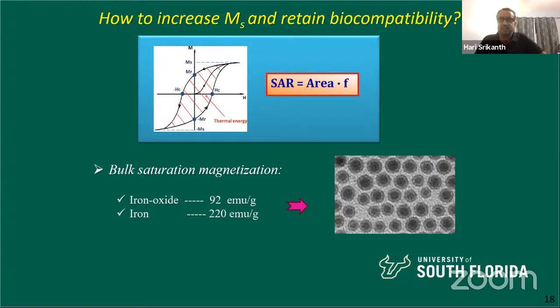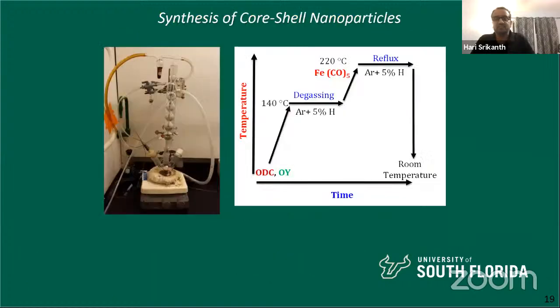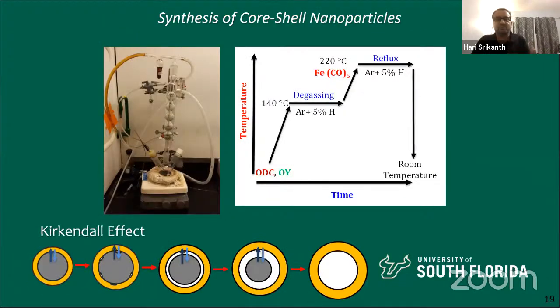So we had an iron core and iron oxide. Because iron oxide is coating the entire core, this whole thing is biocompatible. So we're trying to fool the cells by hiding the toxic iron by covering it with biocompatible iron oxide. So we looked at this, and for those of you that are interested in chemistry, what we do is very simple solution chemistry for synthesis of nanoparticles. But it turns out that when we make these core shell particles, there is something known as the Kirkendall effect.